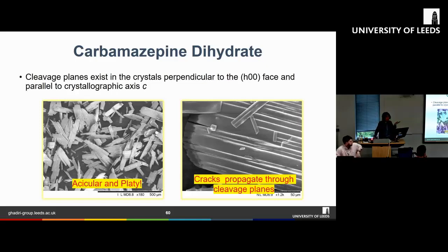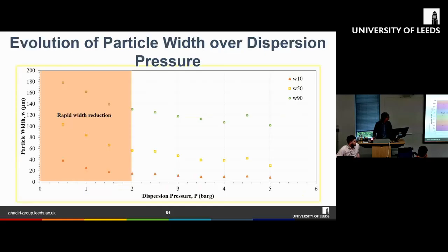And the interesting thing with carbamazepine dihydrate is that we can see very clearly where the water molecules are aligned on the crystals. The region where the water molecules align is also a cleavage plane of the crystal. So the crystal material tends to break along this water molecule channel. Here, just to show you an example, is how the width of the carbamazepine dihydrate changes as a result of dispersion using the Morphologi G3.